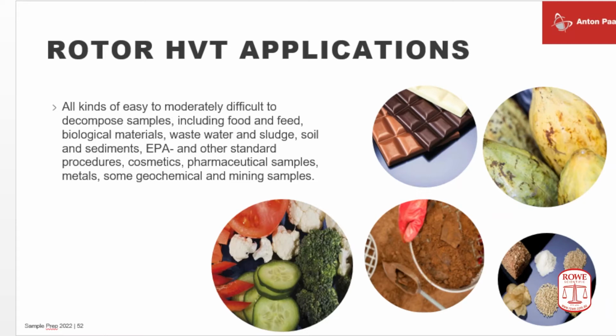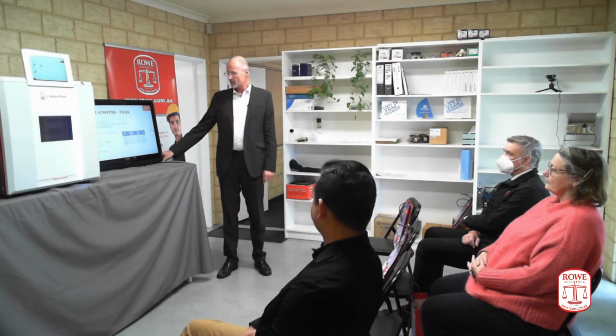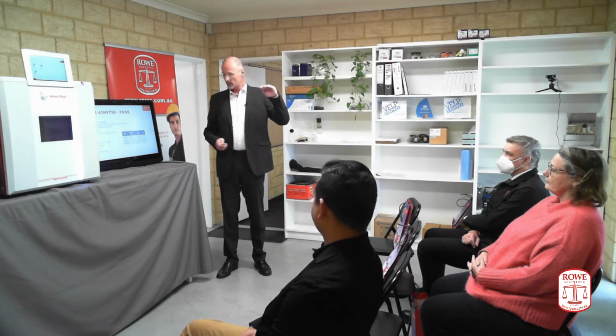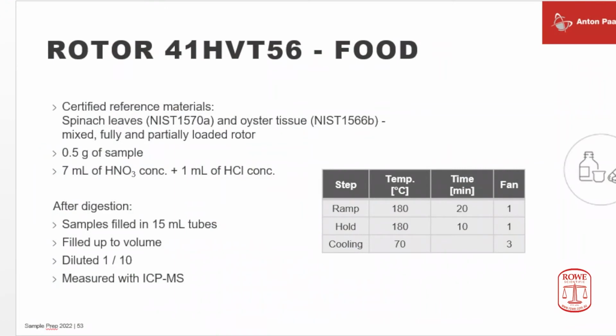So no wonder that this type of rotor also is approved for EPA and other standard procedures for environmental and food testing. It also can cope with cosmetics, pharmaceutical samples, metals, and some of the geochemical and mining samples. A typical temperature profile for food samples, for instance, would be a ramp up to 180 degrees over 20 minutes and hold at 180 for another 10 minutes and then cool down to 70 degrees. So the actual digestion time is only 30 minutes in that case. Add cooling 15-20 minutes. So within 1 hour, including loading and unloading the rotor, a set of 41 food samples can be done.